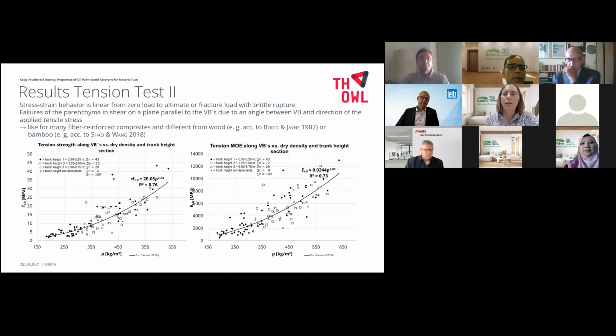The angle between the vascular bundles and the direction of the applied tensile stress results in low strength values. Because of the helical orientation of the bundles with deviations in radial directions, it is not possible to process tensile test specimens with perfectly aligned vascular bundles along the axis of the test specimen. Next slide.